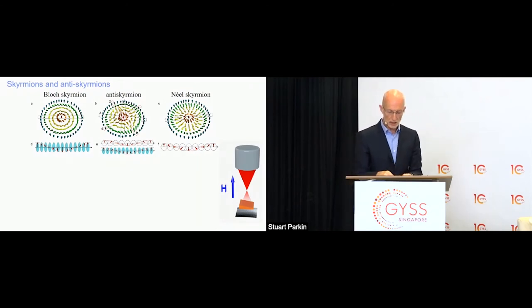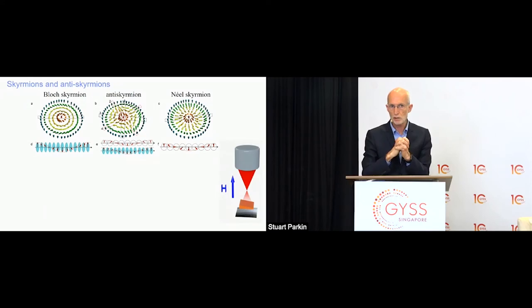So we basically take a single crystal of this material. We use focused ion beam milling techniques to cut a sliver, a lamella, out of this material, which is sufficiently thin that the electron beam can be transmitted through it. And that means it has to be, roughly speaking, below 200 nanometers thick. So we make this using focused ion beam milling.